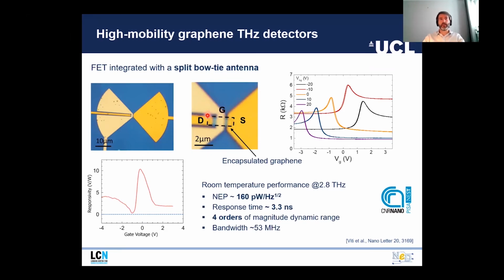Indeed, we applied this high mobility graphene in a device in collaboration with our colleagues in Pisa, in Italy. We used the graphene encapsulated in boron nitride as channel for terahertz detectors. Terahertz detectors work on two different principles. On one side, there is the photothermoelectric effect. On the other side, there is the plasma wave mediated detection. We don't have a lot of time to go into details, but the fact that the graphene had such high mobility was the key enabler to significantly reduce the noise equivalent power, making detectors more sensitive and improving the response time.